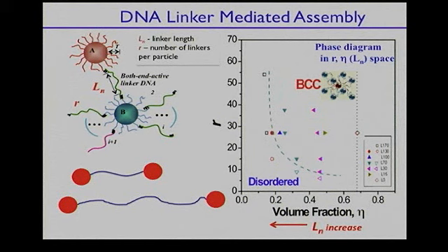What is also important is that we found the minimum number of connections necessary to establish any crystal is somewhere around 8 to 10, which corresponds approximately to how many particles you need to have in a BCC lattice in a corner. And I know some people in this audience may correct me to say that it's not only that, but also some requirement for mechanical stability of three-dimensional systems.